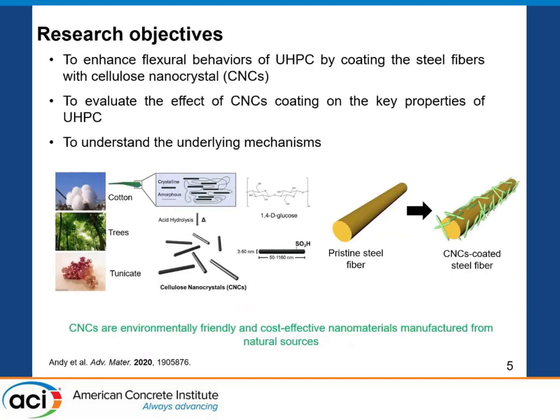Therefore, our research objective is to use a more cost-effective and environmentally friendly coating material, which is cellulose nanocrystals, and to develop an easier coating process to modify the steel fiber surfaces. In this way, we want to improve the bonding between the fibers and the matrix and improve the flexural properties. We will also evaluate the effect of the CNC coating on the key properties of the UHPC and understand the underlying mechanisms. By the way, cellulose nanocrystals are natural materials, manufactured from cotton, trees, and tunicates.